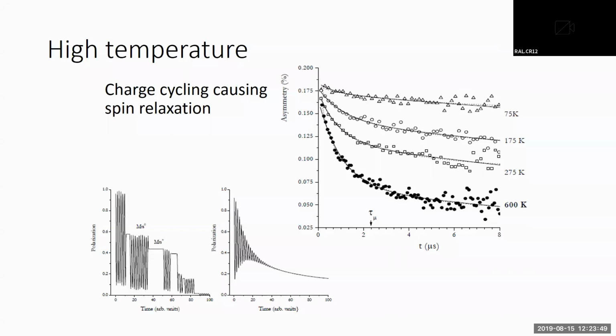In practice, at ISIS with a pulsed muon beam, we don't see this rapid oscillation. You would see that, for example, at a continuous source, and it would correspond to some rapid oscillations here, and you could actually get the relaxation rate of the transverse as well. That tells you additional information about what's happening in the charge cycle. For example, you can tell from this the relative fraction of the times it's spending in muonium versus the diamagnetic states.